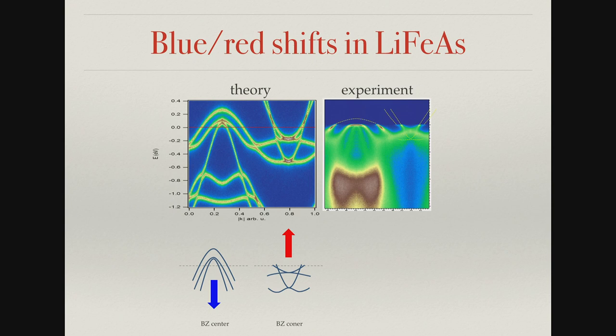Another complication — another way to describe Fermi surface shrinking — we call it blue-red shifts, because this is momentum-energy space. If we compare experiment with theory, we see that dispersions responsible for the hole-like Fermi surfaces in the center of the Brillouin zone and electron-like Fermi surfaces at the corner are shifted with respect to each other. Simultaneously blue and red shifts occur, resulting in the shrinking of the Fermi surfaces that Lara mentioned in the previous talk.